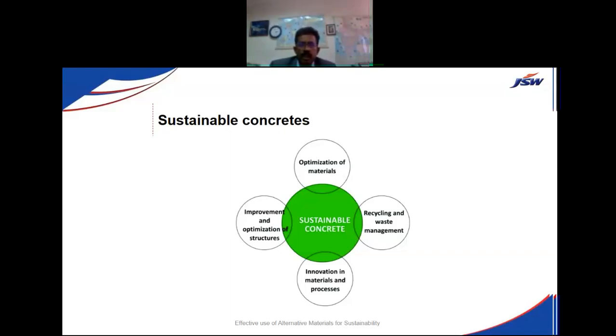We are using fly ash. We are using GGBS. We are using ultrafine fly ash, ultrafine GGBS, metakaolin, rice husk ash, cementitious materials. Lime powder we are using. So like that, we are using optimum material to make the concrete. Recycled aggregates also we are using.